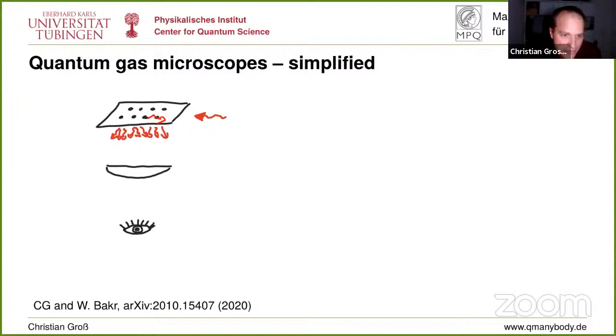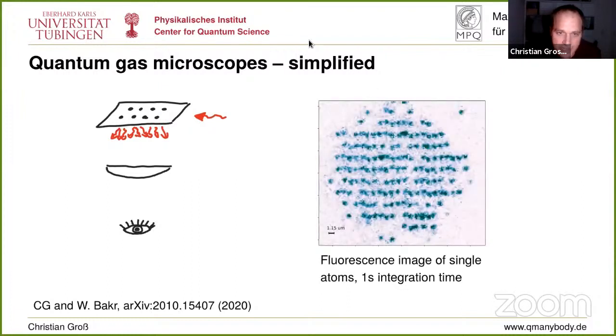And then you collect the fluorescence, and you get images like shown here, where you can really identify in that atomic plane each and every atom as an optical signal on the detector. Again, typical detection fidelities are somewhere around 99%. If you are densely packed, it actually takes quite some time to collect such an image. And these microscopes, I talked a bit about the technology, really were a door opener for many new experiments. There's really a long list of amazing results that came out of these machines.